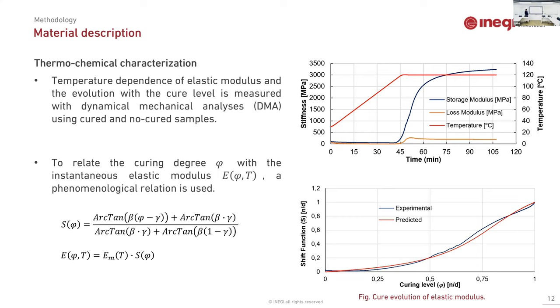Having this data and introducing a phenomenological relation, I can relate how the elastic modulus evolves with the curing degree. It is not a linear relation. This means 50% of the curing degree does not mean that we have 50% of the elastic modulus developed. It's something different. This is an equation. We have some fitting parameters. I have experimental data, so I can do the fitting. And with this relation, I can predict how the elastic modulus evolves with the curing degree and changes with the temperature. Okay. This is another ingredient that is required to do the analysis.